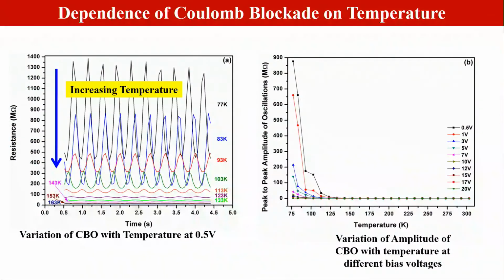Here we have played with bias, because people have done this with transistors, 3-terminal devices, but here we have done it with 2-terminal devices. We have seen that when you increase the temperature, the Coulomb blockade disappears, but on the lower side, if you go towards lower and lower temperature, the amplitude of oscillations is very, very large. The same thing happens at defined bias, this is just 0.5V, as a function of the bias across the 2 terminals, and we see this is the Coulomb region where it plays a very important role. High temperature means the Coulomb blockade disappears, but if we go to low temperature as well as low bias, this is our region, we can play with devices as we like.